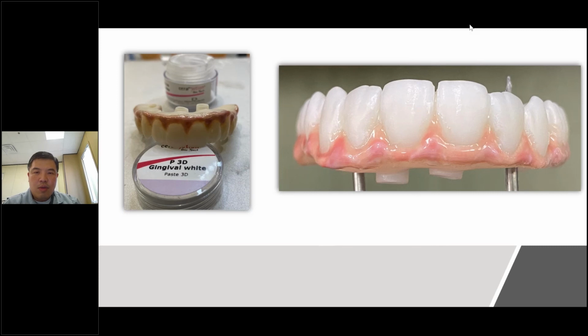Okay, so with that, what it means is that once it hits the high ramp, it gets to 850 or 750, depending on what kind of porcelain you use. It has to stay in the temperature for 2 minutes, and then it starts ramping down. Ramping it down with the chamber closed.